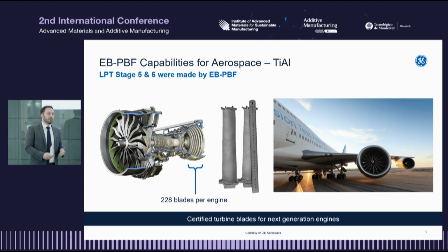Because this material is an intermetallic, it retains its order through very high temperatures, so you don't have a phase transformation like Ti-6-4 might. But when you try to make this conventionally through a spin casting technique, you get lots of cold shuts and the yield is quite low. But electron beam processes in a high temperature atmosphere, so you can do a lot of welding of these traditionally very hard to weld materials.